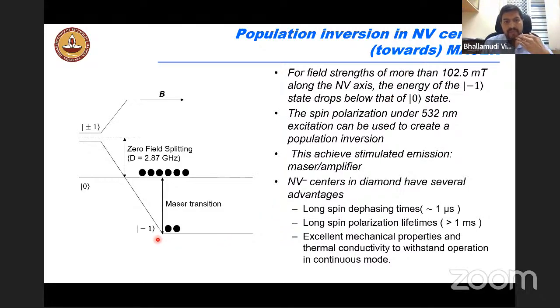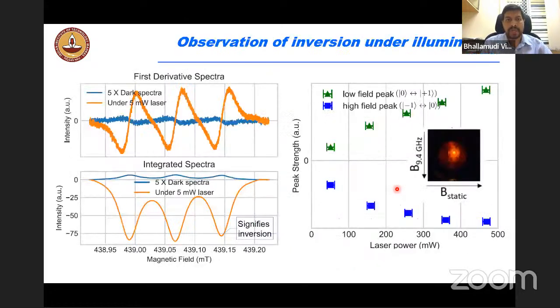But as it happens in NV, if you apply a large enough field, this triplet -1 level can come below the 0 level. But now you can initialize the spins at the 0 level itself using the laser pumping that I said, which means that you can create a population inversion. And this population inversion, coupled with the long spin lifetimes in NV, and the fact that NV is a very good thermal conductor, so it can dissipate all this laser pumping power that you're putting in, makes it ideal for building towards a maser.